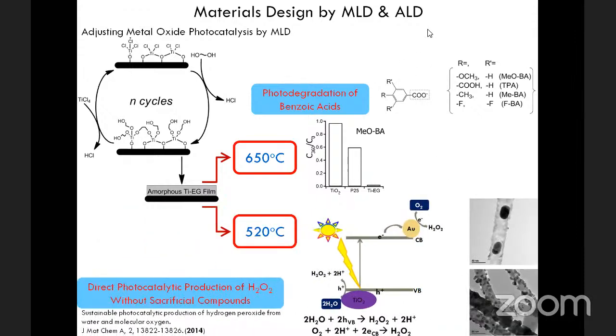So we tested the photocatalytic activity of titanium ethylene glycol annealed at different temperatures for benzoic acid. And here you can see a comparison in the reactivity comparing titanium ethylene glycol, the P25 nanoparticles, and pure TiO2. And you can see the lower the graph, the higher the activity. So you can see that indeed these films annealed at 650 degrees Celsius are much more active than pure TiO2, but also much higher than the standard used, the P25 nanoparticles.